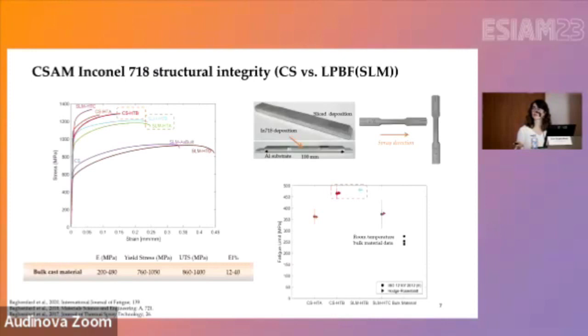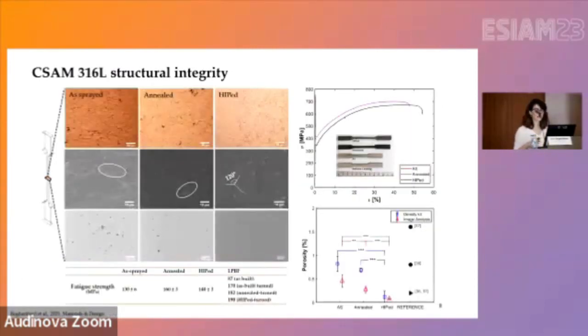And here you can see the results also for actual fatigue tests of the samples, comparing the results for SLM and cold spray, with a very comparable fatigue limit at room temperature. Also, the results compared with, let's say, bulk cast material obtained with classic manufacturing techniques are in line with what we could get for these samples, which were Inconel 718. Here you can see also the results for 316L.